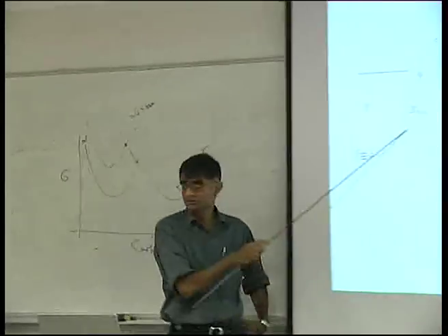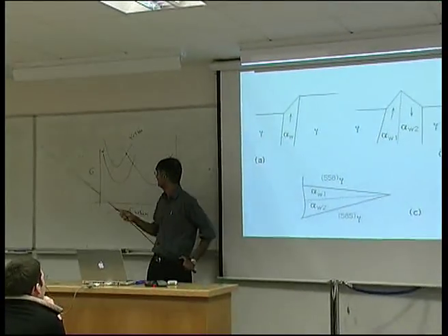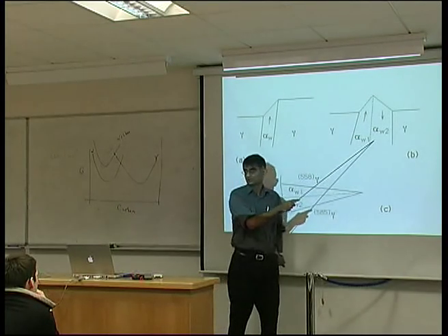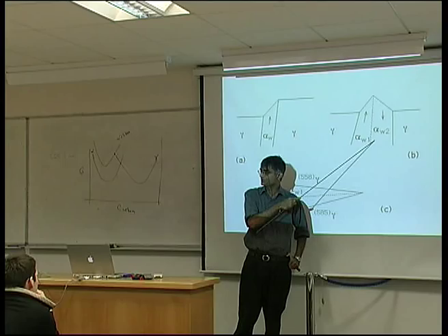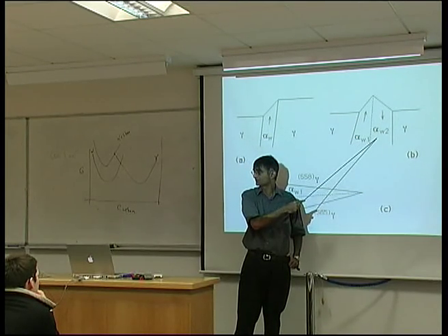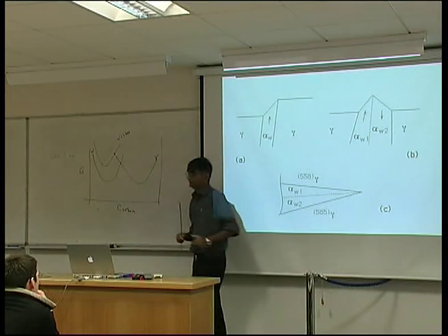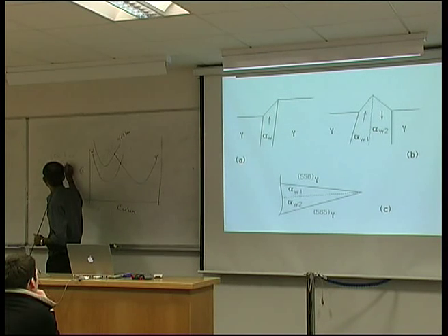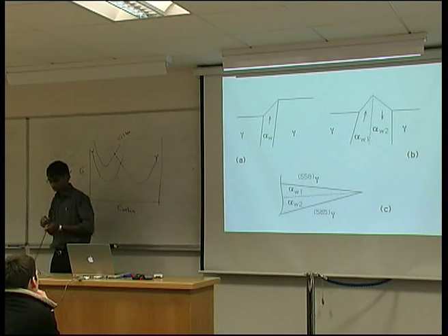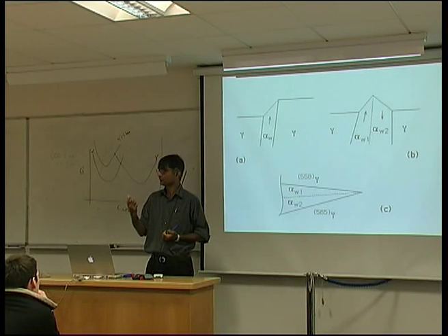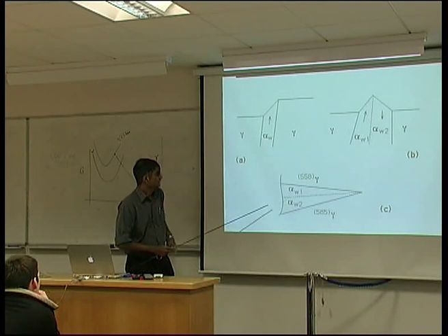Instead of forming individual plates, like this, where the strain energy would be that much, you form two plates together, which tend to cancel out each other's shape change. So one plate shears in that direction and the other one in that. But in that way, you can reduce this term to something of the order of 50 joules per mole. Now, there is a cost to this, and that is that you have to nucleate the right two plates at the same time. Okay?